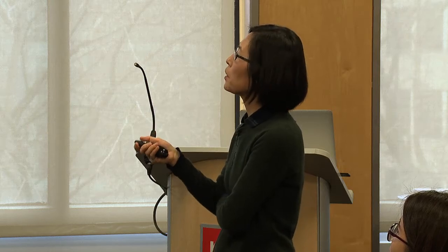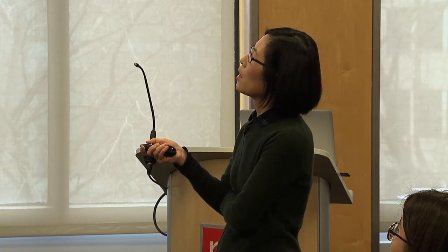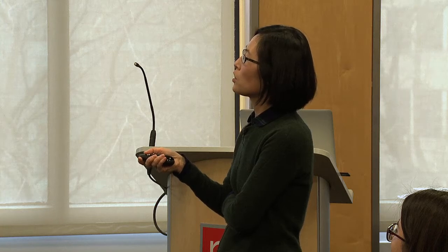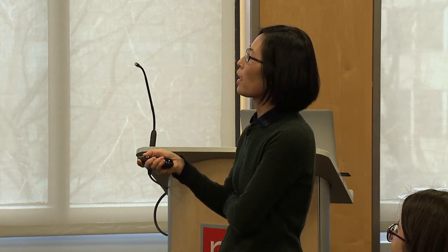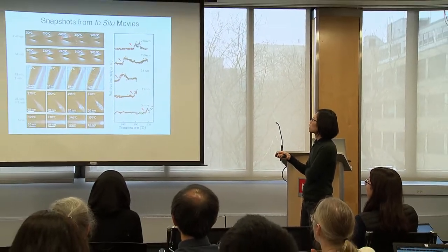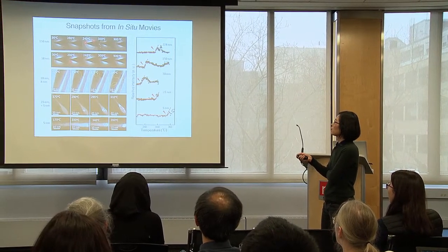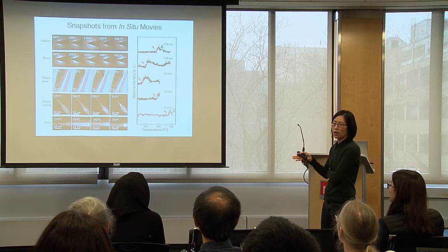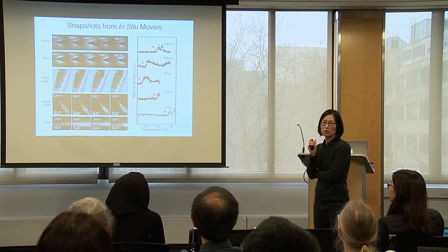So we just go ahead and do it as a function of a number of different nanorods. Just repeat it. And the onset of crystallization temperature, we try to quantify this by doing the following. We know the regions that do not crystallize because you just watch the movies. So we looked for intensity contrast, or the contrast jump, compared to this region versus some background region. When the slope changes, right at the onset of the slope change for the intensity contrast, we call that T sub x, onset of crystallization.